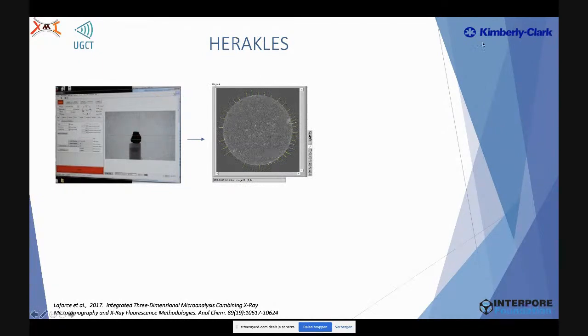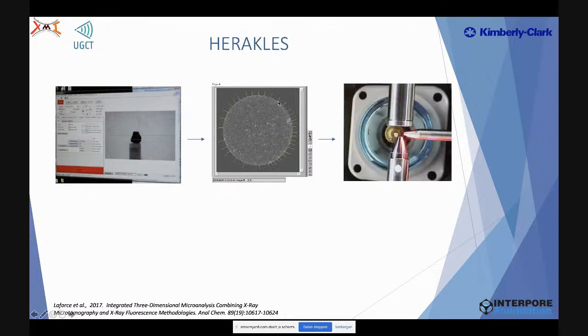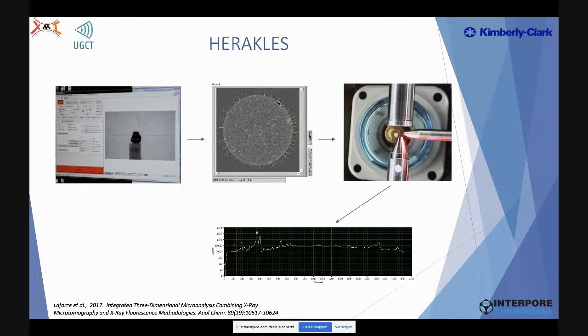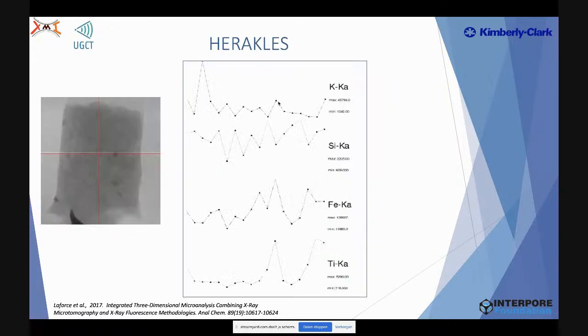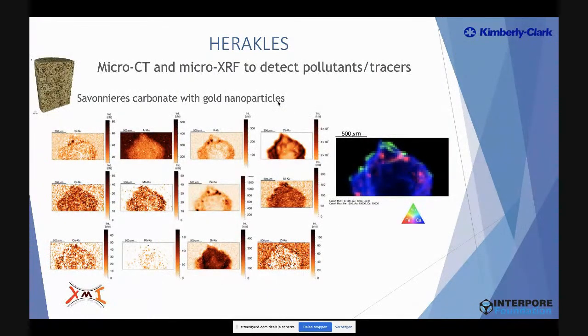And so this allows us to first take a sample, scan it, and based on the reconstructed image, select an area of interest. For instance, say, okay, I want to have a point analysis at this spot. Then it automatically goes to that spot, does the measurement, and you get the point analysis. Similarly, you can also draw a line and do a line profile, or you are able to do mapping of your elements.